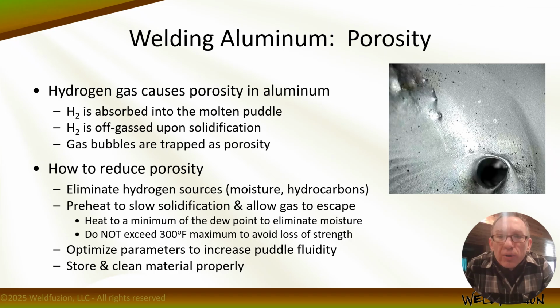Double and triple check your shielding gas flow rate and all connections to make sure you have enough gas flow and that you don't have any leaks, because any leak can vent gas, and also if the velocity of the gas going through it is substantial, it can actually suck in atmosphere through that leak. So we want to make sure that we're not pulling in any atmosphere or moisture. At the same time, if we're talking about shielding gas, inspect your consumables. Make sure that you don't have a clogged nozzle or any clogged gas ports up in the head of your torch. Clean those things out, maintain them, and usually you can work through this if it's your primary issue.